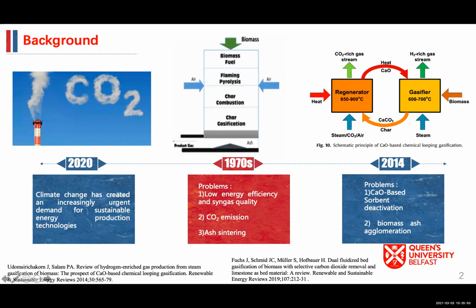In order to improve the performance and scale up traditional biomass gasification, calcium oxide looping biomass gasification has been proposed and investigated by many researchers. As you can see from this graph, the mechanism of this technology is to utilize calcium oxide as a sorbent to capture CO2 in order to move forward the equilibrium of multiple reactions during gasification, especially the water gas shift reaction, to get a hydrogen-rich syngas. However, it has several problems such as calcium oxide-based sorbent deactivation and biomass ash agglomeration.